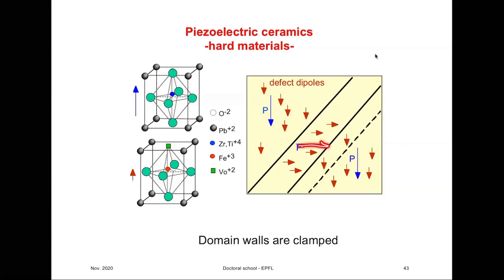And imagine that we have here a 90-degree domain wall, and then that we apply electric field to move this domain wall down. So we are applying electric field in this direction. Now, to do this, normally if a material is non-defective, all we have to do is to move titanium from one potential well to another, and that's it. Here, the situation is much more difficult. Not only that we have to move this iron, which may not move at all because that unit cell, it's not even sure that it is ferroelectric. We actually have to rotate this, we actually have to rotate to move this oxygen vacancy from this position to this position or to this position.